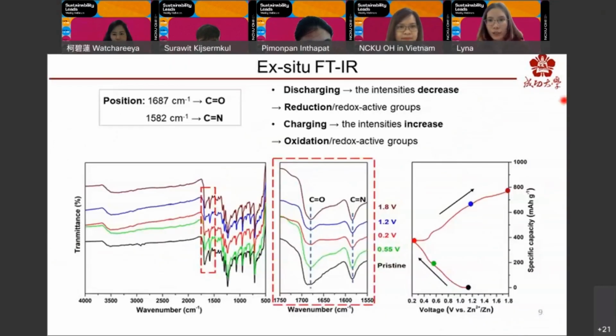The change in the carbonyl and amine groups was first confirmed by using FTIR spectra. There are two strong peaks belonging to carbonyl and amine groups. During discharge, the intensity of these two peaks decreased, indicating the reduction of the two redox active groups. During charge, the intensity of these two peaks increased to the initial level, suggesting the oxidation of the redox active groups.